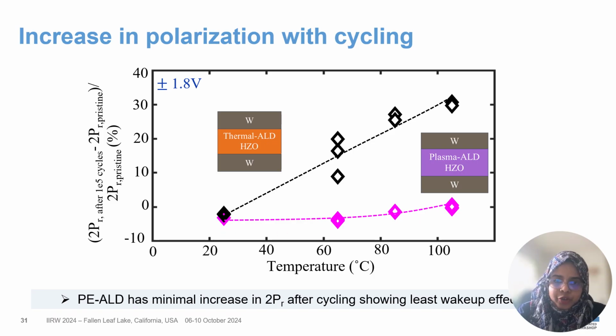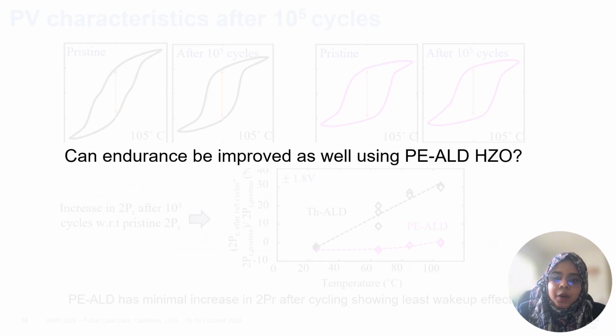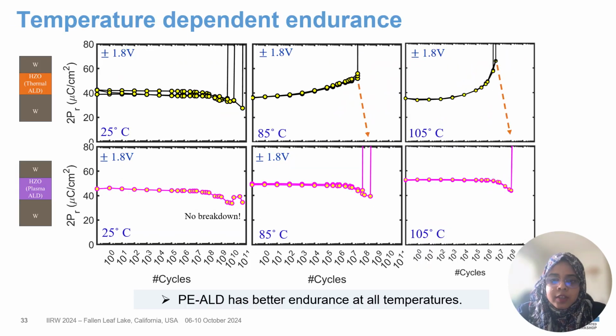Now let's see how the endurance of both of these samples looks like, and if we can get better performance on the endurance side when we are using the plasma ALD HZO. So we have measured the endurance of both the devices. The top panel is coming from the thermal ALD device and the bottom panel is coming from the plasma ALD device. So you can see that at 25 degrees Celsius, for 1.8 volt application of bipolar pulses, we don't see any breakdown in our plasma ALD device.